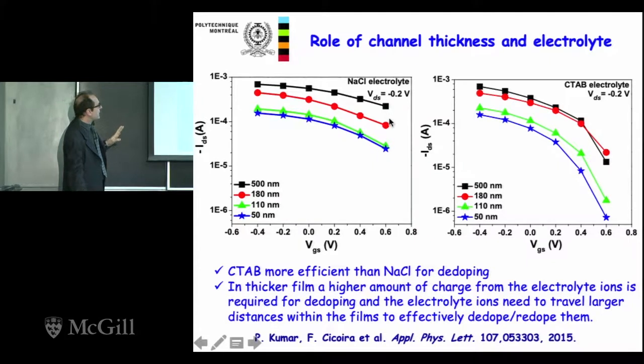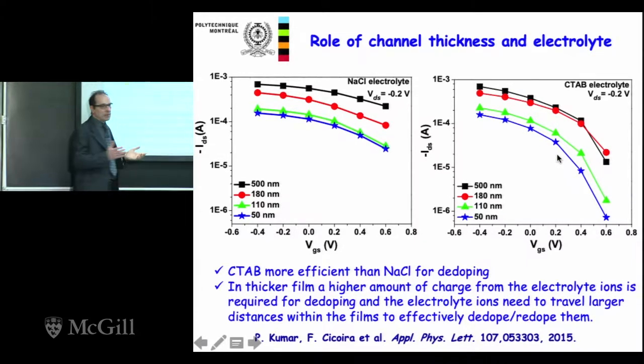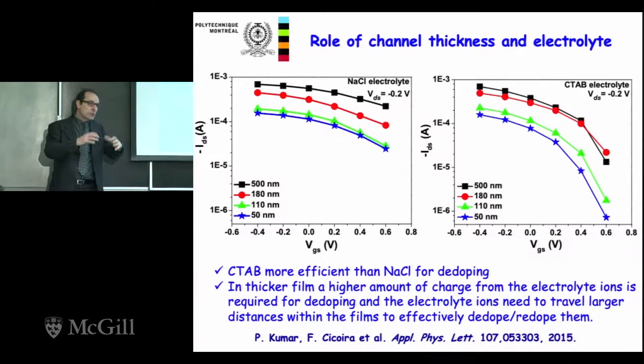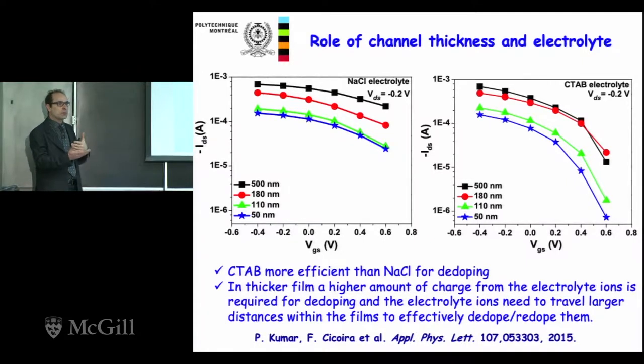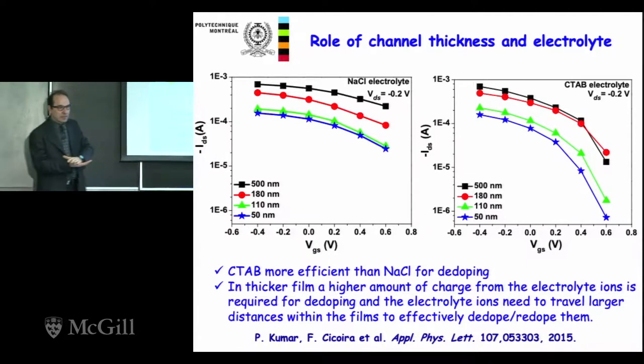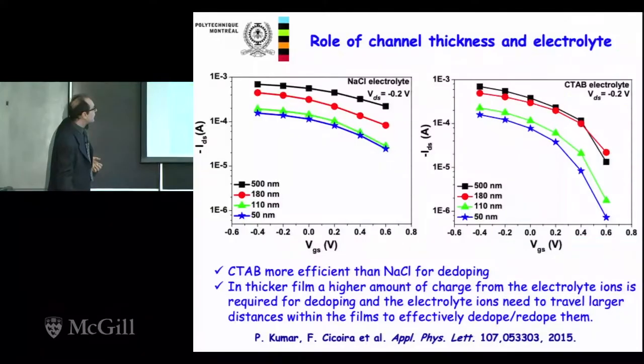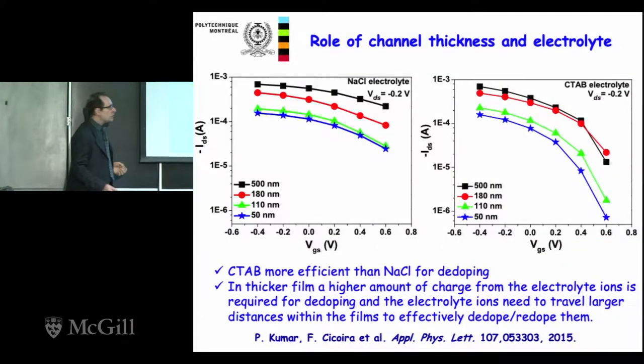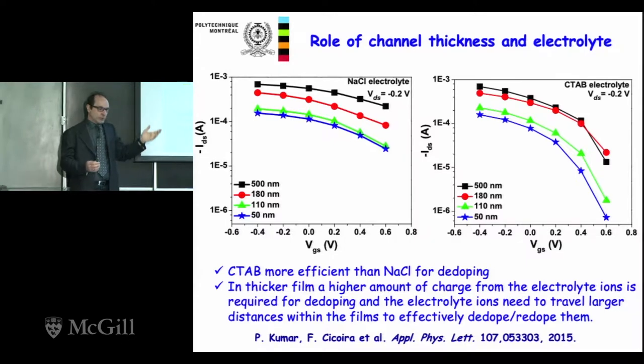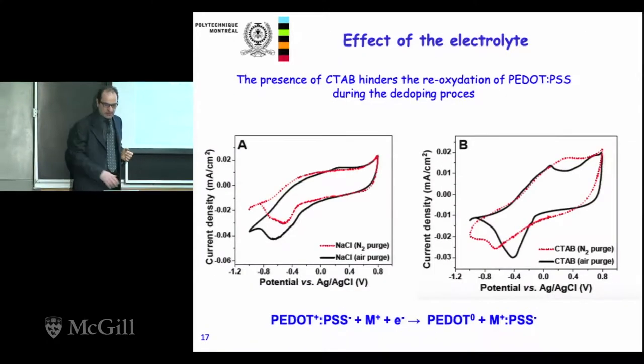The other thing you can notice here, which gives you also an idea of the effect of the parameters, is that these plots are at different thicknesses. You can see that the higher the thickness of the material, the more difficult it is to achieve a high on-off ratio. This is because the working mechanism of these materials includes all the bulk of the material. It's not like a field effect transistor where only the interface between the semiconductor and the gate dielectric is involved in the working mechanism. But here, the doping, de-doping process takes place in the bulk of the material. So if you have thicker films, it gets more difficult to de-dope. So this also tells you that the performance depends on the device thickness.